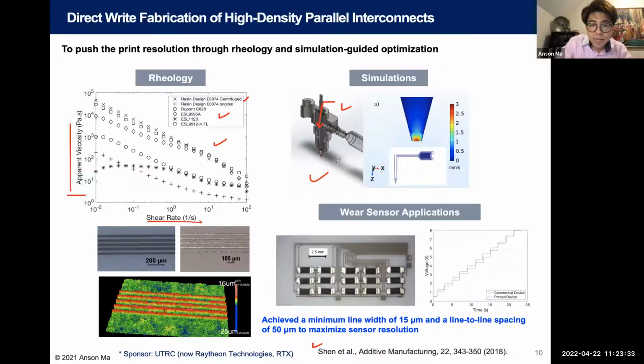But once the material is deposited onto the substrate, the viscosity goes up, because on the substrate, you're not really actively shearing the material. So in that case, you'll be looking at a low shear or even zero shear viscosity. So the higher the merrier, right? In other words, shear thinning is usually advantageous for this type of printing, because during the pumping or pressure action, you bring down the viscosity, but as soon as the material is deposited on the substrate, the shear rate diminishes, meaning that you're moving in this direction in a viscosity plot, and then the viscosity goes up. So you maintain the shape fidelity of whatever you just printed. So in general, it is a good thing.